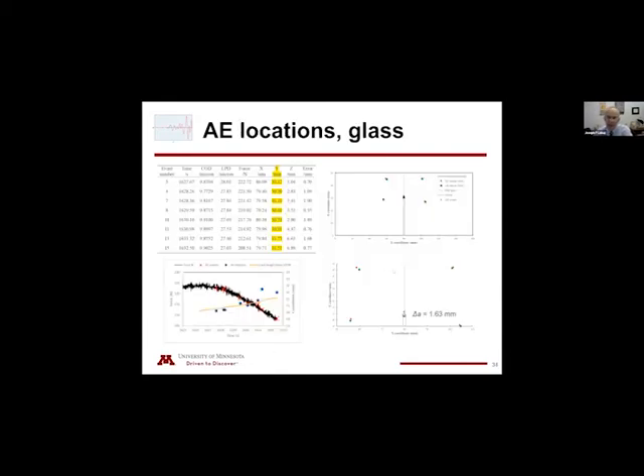Okay, locations are beautiful, right around the notch, and this is the deep notch. So this is the 30mm notch in the 50mm beam. This is a blow up of those locations, and this is a tracking of those locations. The locations are well tracked by the yellow or orange line, which is what would be predicted from linear fracture mechanics. So, okay, we're not doing well here, but this is a small scale, off by maybe 1 millimeter. And this indicates the location error. This one has slightly larger error, 1.7.